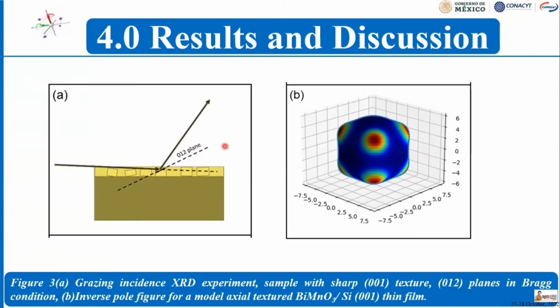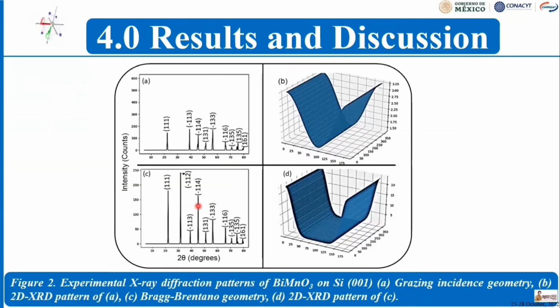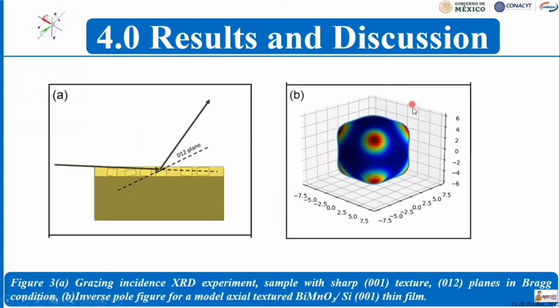Also, the crystal plane 0 1 2, at an angle of approximately 26 degrees, is not visible in the grazing incidence geometry. We have the inverse pole figure for the textured bismuth manganese oxide.